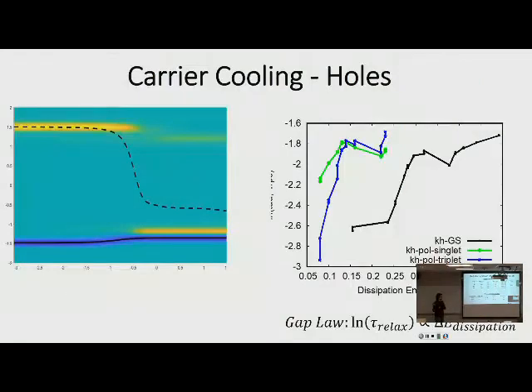Can you go one step back? The green and blue curves are above the red curve. They're higher. You mean the black curve? On the right side, there are three curves: ground state, positive polaron singlet and triplet. So the relaxation for polarons is quicker than for the ground state. It's the same for orbitals with the same symmetry. So the polaron doesn't slow down the relaxation. Right, it enhances the cooling anyway. It speeds up the cooling.